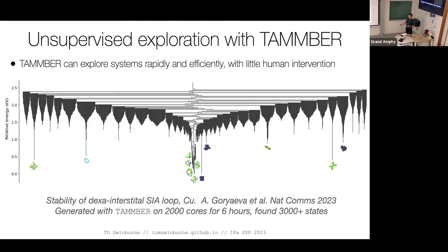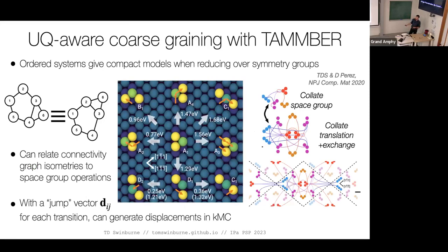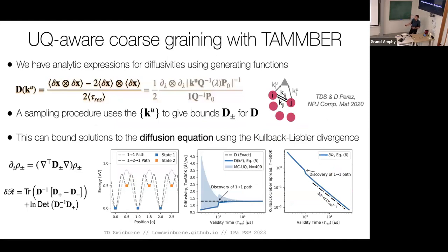We can look at simpler systems with periodic symmetry, like a simple surface. Using that periodic symmetry to restrict the number of states, we plug them into our Markov chain and produce diffusion constants as a walker-with-death process. Before being absorbed to the unknown rate, we displace and produce a diffusion constant. Propagating through that walk-with-death problem to a random walk, we get sensitivity of the diffusion constant with respect to unknown rates — an uncertainty quantification. We can propagate that in a Monte Carlo sense to get bounds on diffusion and a convergence metric.